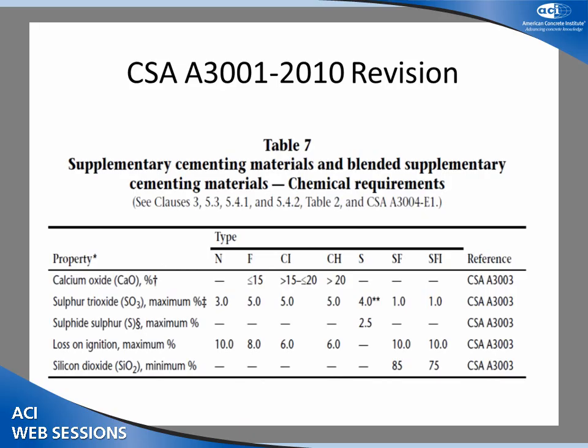The top line there, the F ash, CI, and CH, it's all regulated based on the calcium content of the ash. And then we combine some natural pozzolans, just like the US F, CI, CH, and we've got slag, silica fume, and we've got a lower SiO2 silica fume as well. They're all in one table in the standard. And so the only thing that applies to ash, really other than sulfur trioxide and loss on ignition, is calcium.